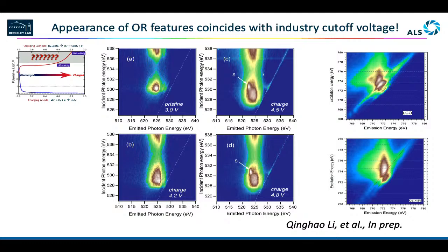You're still using that in your cell phone, the smaller scale batteries, because at the smaller scale you can afford to have a pure, expensive cobalt base, because it gives you the highest volumetric energy density. Your cell phone and some of the laptops are still using pure lithium cobalt oxide. In industry, if you make lithium cobalt oxide into a commercial battery, they never go beyond 4.2 volts. So 4.2 volts is almost right at half of the lithium you can pull out.